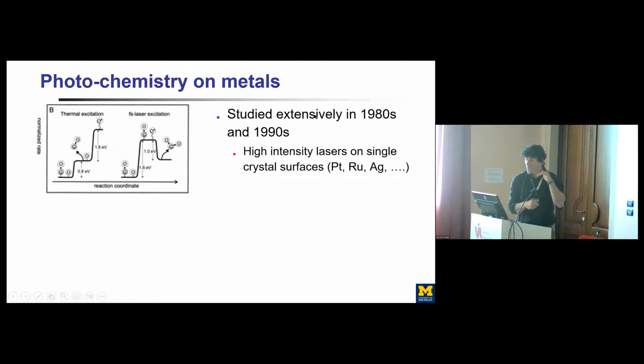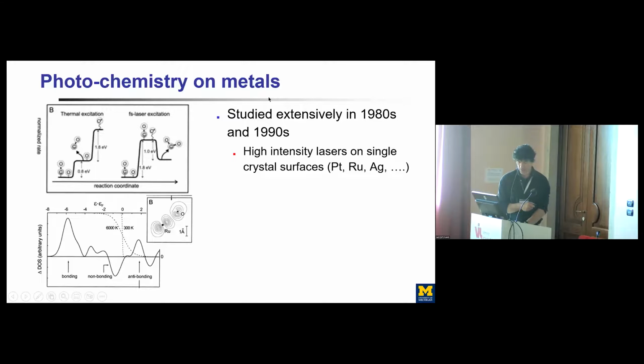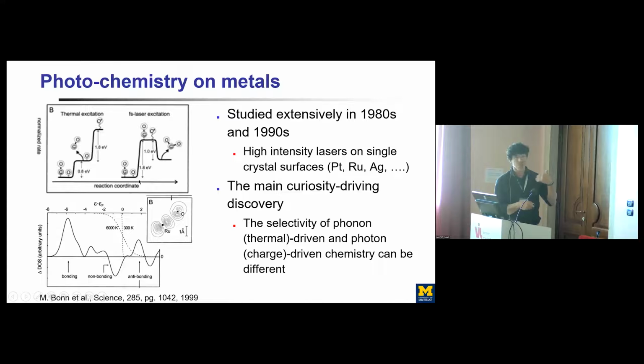On the other hand, if you shine a high-intensity laser on the same surface, prepared the same way, you actually get CO2 formed. And what they proposed through a series of calculations and experimental studies is that when you shine laser, you create these energetic electrons in the ruthenium surface, and these energetic electrons excite your oxygen. You create this excited form of oxygen, and this excited form of oxygen reacts with CO to form CO2 before CO would desorb. So the main curiosity driving the discovery of these experiments is that the selectivity of these thermal processes, meaning a process that takes place when you heat the surface of the material, and the selectivity of these charge-driven processes, basically light-induced processes, can be very different.